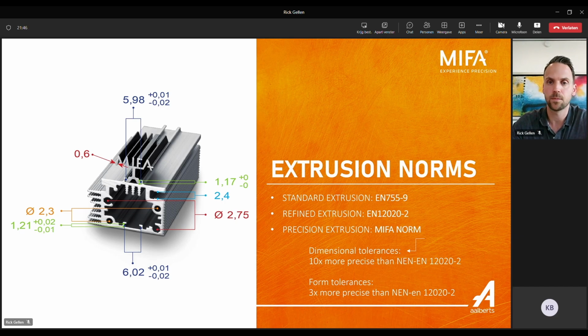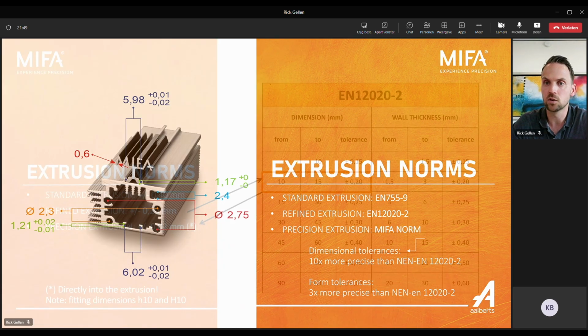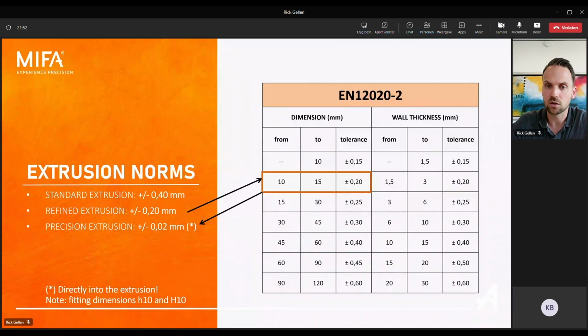What does that say? On the right side you see a cutout of the EN12020-2. That means on a dimension from 10 to 15 millimeters, you get a tolerance of plus minus 0.2 millimeters according to the EN12020. For the mass extruders, they say, yeah, at us this is plus minus 0.4 millimeters. But Mifa, we dare to say on this dimension you get 0.02 millimeters, and that is directly out of the extrusion on tolerances. So that is really the precision we can extrude directly out of extrusion. And this is really unique in the world of extrusion.